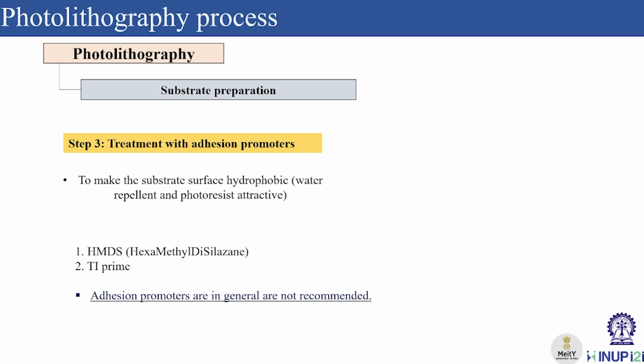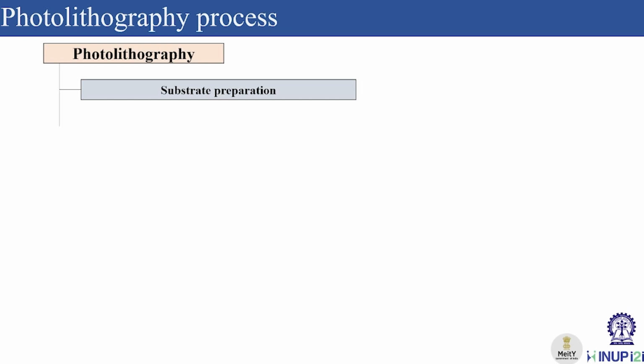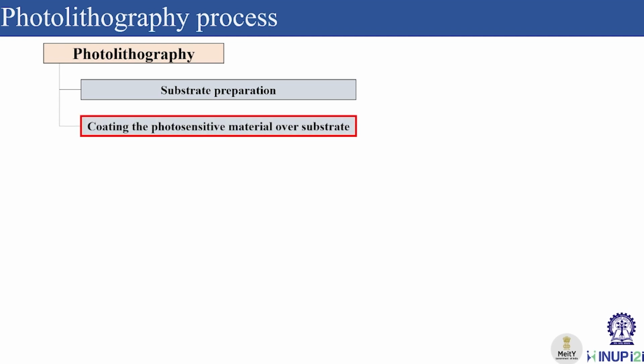But in general, adhesion promoters are not recommended, because for post photolithography processes such as lift off and etching processes, these chemicals can prove to be fatal. So in general, we don't use them and we won't be using them in our lab too. The next step is coating this clean substrate with the photosensitive material.